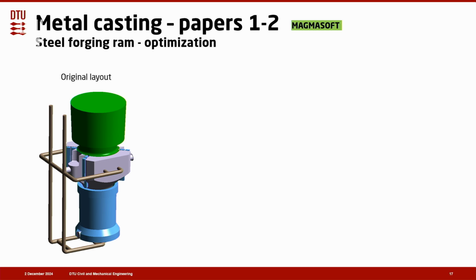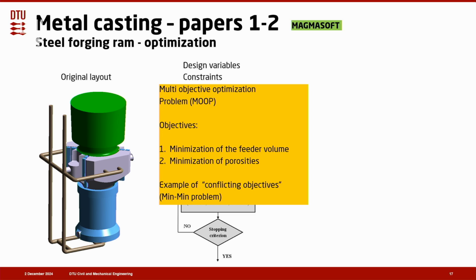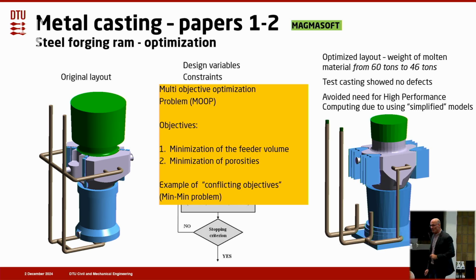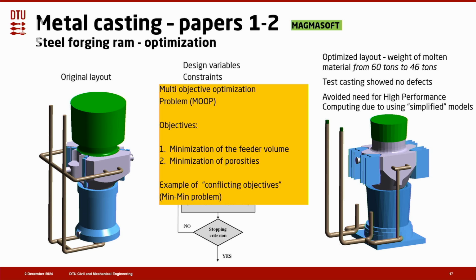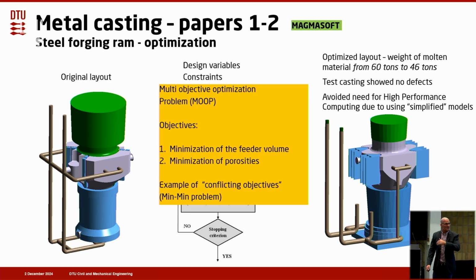People would know that solving Navier-Stokes equations is for sure not simplified, but this was at a scale where these phenomena normally do not take place. So it was actually simplified. And then we did a multi-objective optimization problem where we wanted to get rid of those centerline porosities, but also make it more energy efficient. So we found the optimized layout. The weight of the molten material went from 60 tons to 46 tons. It was a success. It was test cast, and it showed no defects. And this was obtained by this relatively simple model, calculating many scenarios, and then we could optimize and ask the computer, please give us a layout that gets rid of the defects.